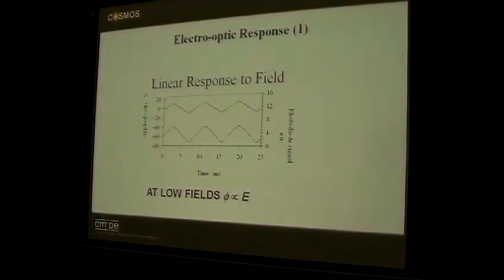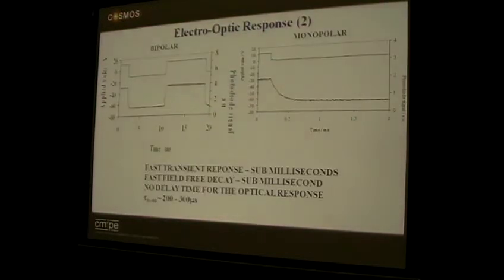But first of all, I said the response was linear in the field. There's the applied field, and there's the optical response. The signal is following the voltage. We are following the field. The response time, is it fast? Yes, the answer is there's your length scale, 0 to 10 milliseconds. And the decay time, or the switching time, is of the order of 200 to 300 microseconds.